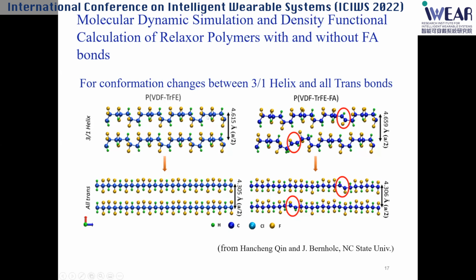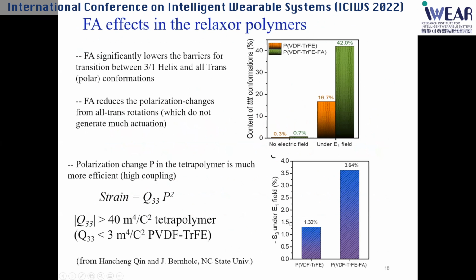So for both PVDF TFE and PVDF with FA, you can see you can realize this transition between non-polar and polar conformation. But the difference here is, with the electric field, as I said, the double-bonded FA reduces the barrier for the transition between different conformations. So you can see, with the same electric field, with a polymer without FA, you only generate transformation between, for example, at this electric field, from the non-polar bond to polar bond, only about 16%.